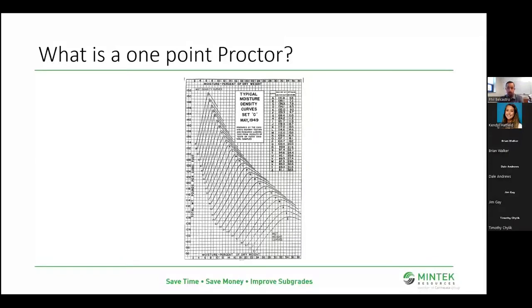Some agencies out there have literally done thousands of proctors to develop what they call a family of curves. A one-point proctor is used to choose the curve that represents the soil you're looking at. You can quickly pound out one proctor mold, see what your density and moisture are, plot that in this family of curves, see where they intersect, and use that to see what your OMC is, what your target should be. If the intersection of the moisture and density falls on a curve, bingo, move on, use that curve. If it falls between curves, some say to interpolate, but I think most just go up to the next highest curve. So that's a one-point.